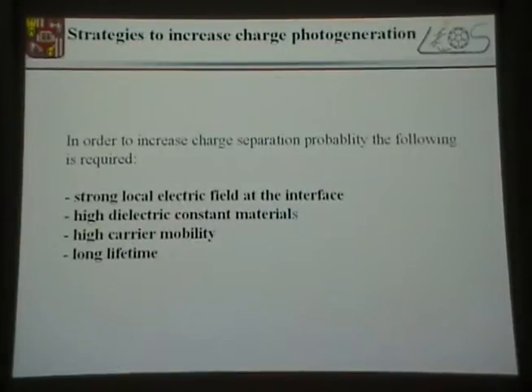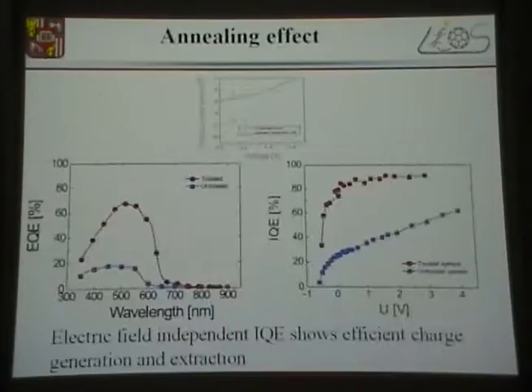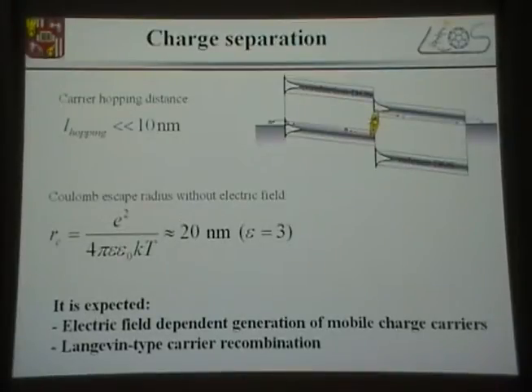The strategies are, of course, we have to increase the local electric field between donor and acceptor. We have to use higher dielectric constant materials, because as you see, this is the equation defining the Coulomb radius. If we use higher dielectric constant materials, of course, the Coulomb radius would be less, and separation would be more efficient.